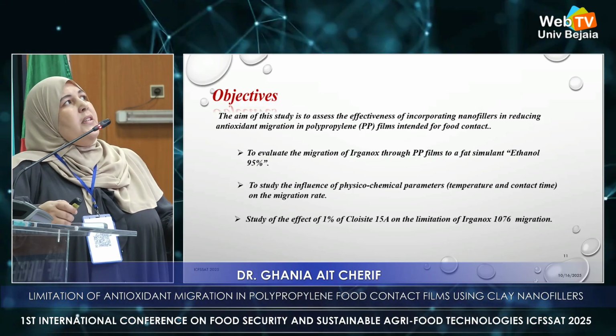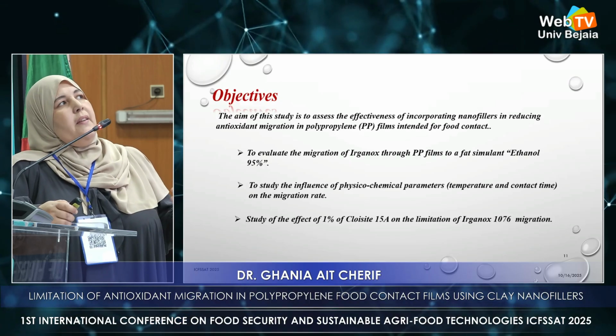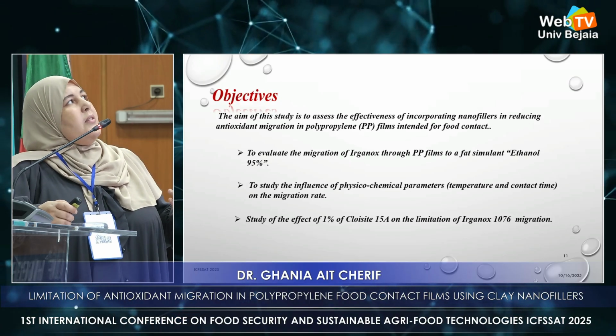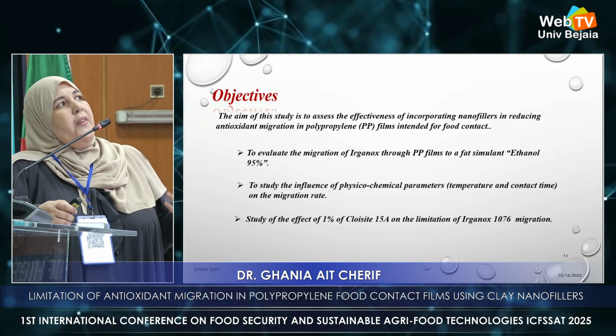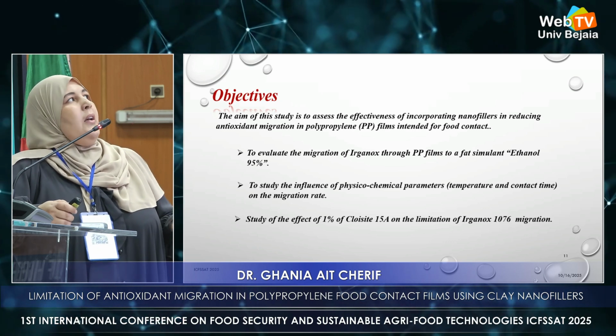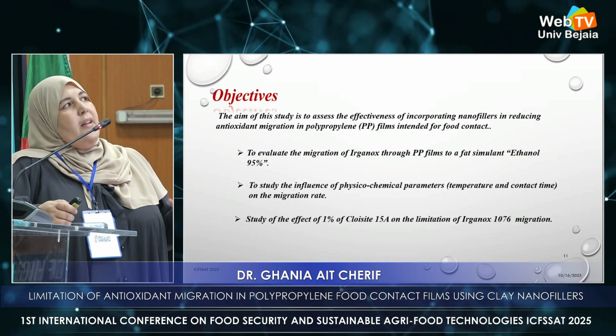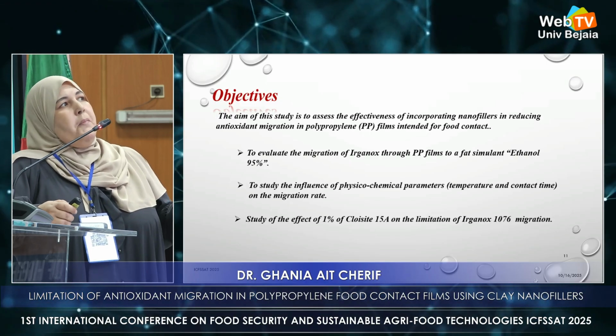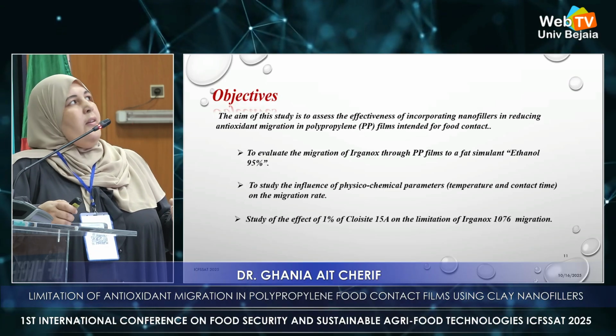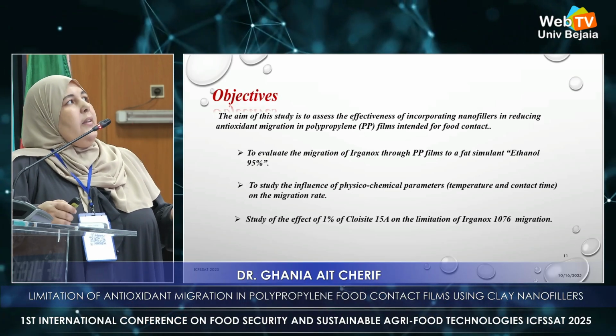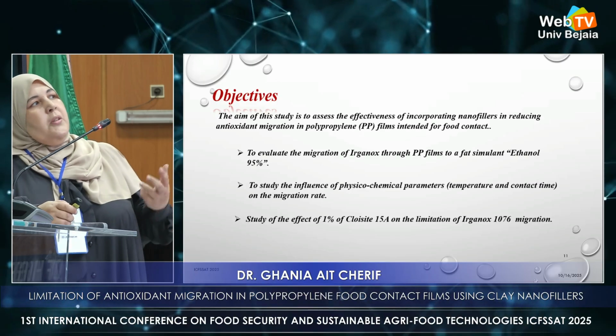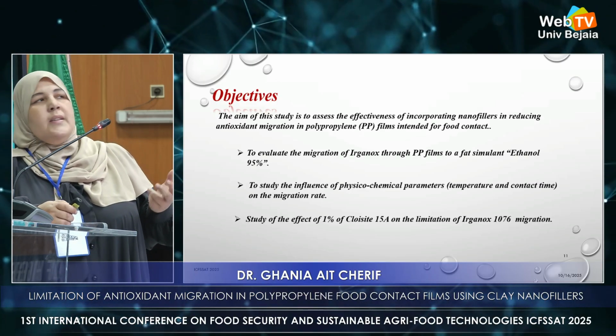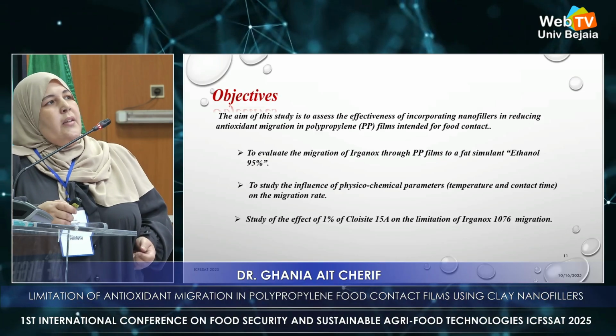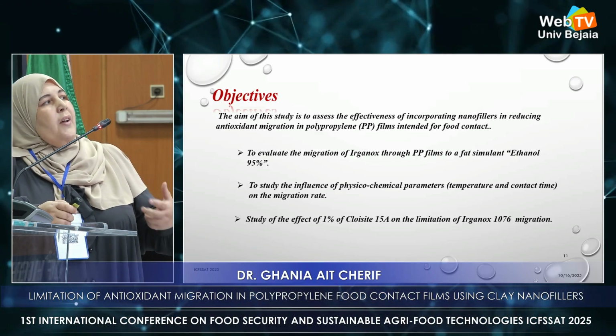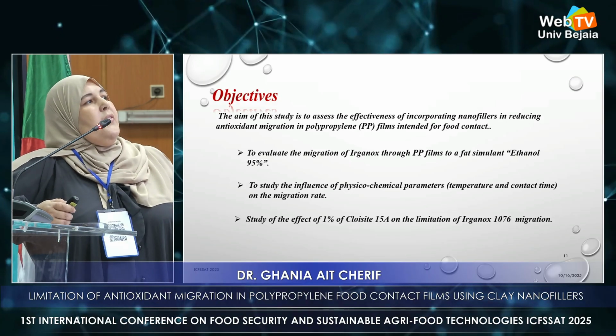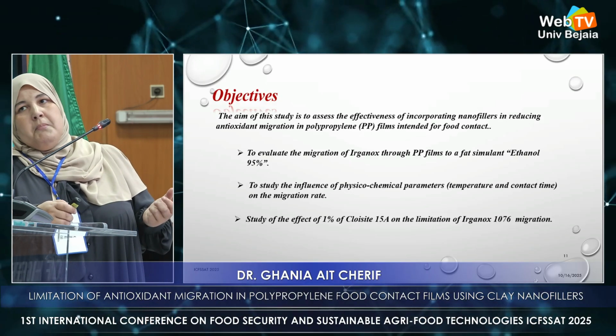The aim of this study is to assess the effectiveness of incorporating nanofillers in reducing antioxidant migration in polypropylene films intended for food contact by evaluating the migration of Irganox, which is a stabilizer, through the PP films to a fat simulant, which is ethanol 95%. Secondly, by studying the influence of physicochemical parameters such as temperature and time on the migration rate. Third, by studying the effect of adding 1% of Cloisite 15A on the limitation of Irganox migration.